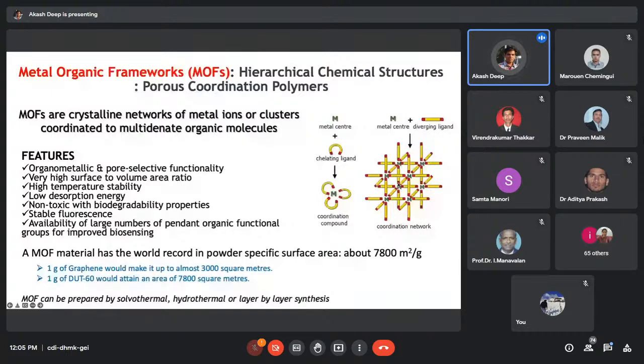They have a very high surface to volume ratio. In fact, MOF material has the world record in powder specific surface area, 7,800 square meters per gram. Here the comparison is given: graphene, which is a very well-known nanomaterial, if we take 1 gram of graphene, it takes around 3,000 square meters of area. But 1 gram of this DUT-60 MOF will cover an area of 7,800 square meters. So you can see how much larger the surface to volume ratio, the area ratio, of the MOF is.